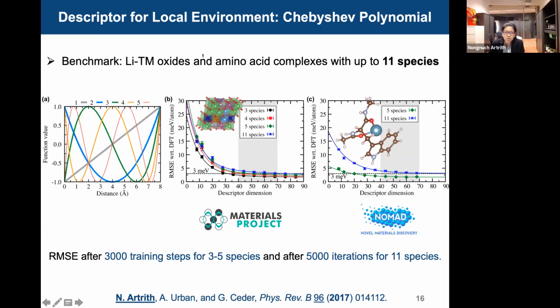So we test with many different chemical species that we extract from the Materials Project. This is the lithium transition metal oxide rock salt structures that contain many different chemical species: 3 chemical species, 4, 5, and 11 chemical species, like you can see here. So most of them really show the numeric predictions with really low errors. In this case, we already have the convergence at 3 meV per atom.